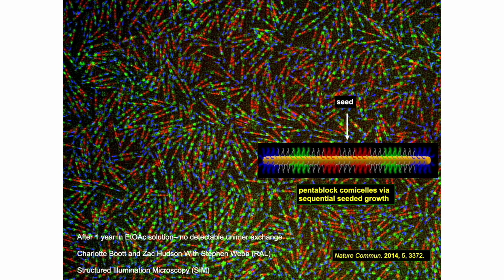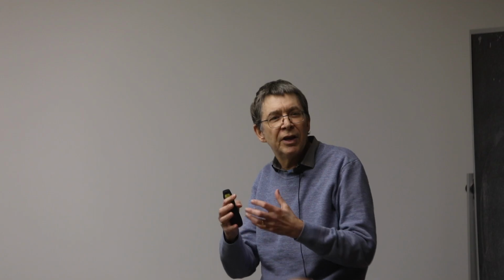So you can add a polymer with a red dye, then one with a green dye, and finally one with a blue dye, making this block structure with multiple fluorescent dyes. This is a fluorescence micrograph in solution of what you can make. When we saw structures like this, we were very excited because no one could do this before—in the past, people couldn't even control the shape of the micelles very well.